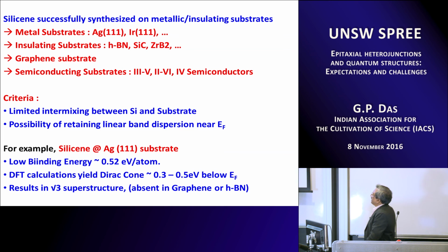Let's take the example of silicene on silver 111 substrate. This work has been done by the group of Gilles in France, and look at the value of the binding energy. The binding energy is about half an electron volt, and the DFT calculation yields a Dirac cone which is about 0.3 to 0.5 electron volt below the Fermi level. And it also results in a root 3 superstructure which is absent in either graphene or hexagonal boron nitride.